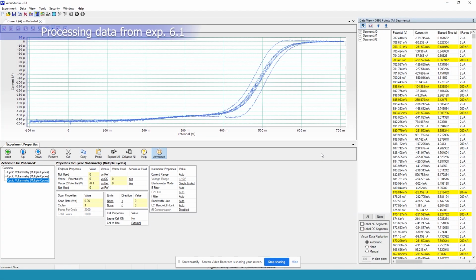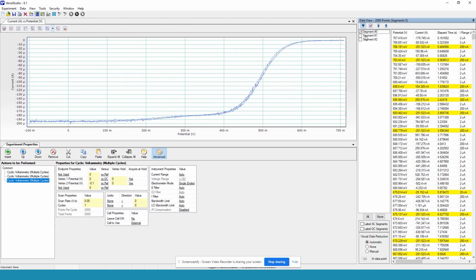So these are the results that we got from this rotating disc electrode experiment, and we can quite clearly see that the results are significantly different from what we are used to. Now, to explain this, I'll open only one experiment for now. We can quite clearly see that we no longer have the formation of a peak, but instead the current seems to level off at a plateau value.